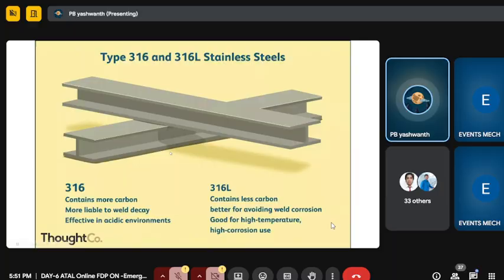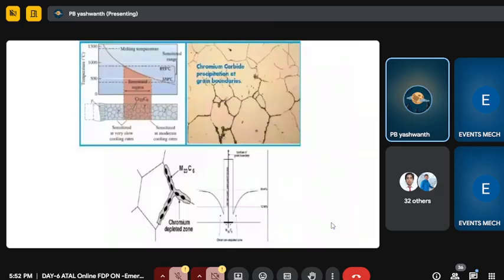So here we should understand what 316 and 316L stainless steels are. Both are austenitic stainless steel. In the gradual evolution from 316 to 316L, 316 contains a little more carbon, whereas L stands for lesser carbon. 316 is liable to weld decay, it has weld issues, whereas for avoiding the weld corrosion, you have a lesser amount of carbon, effective for acidic environments. 316L is not just for high temperature, it also has high corrosion resistance.